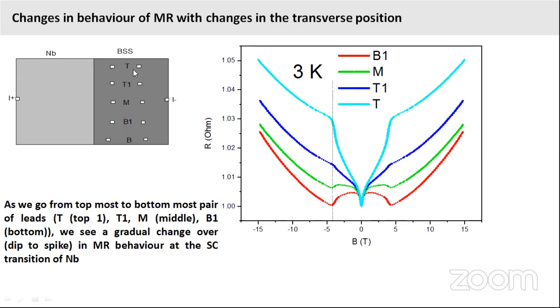As we move from top to bottom, we observe that at the top there is a spiking in the MR, and then as we move down to this T1, there is a decrease in the amplitude of the spiking, and then as we move lower, there is a dip, and the amplitude of the dip increases when we come further to the bottom. This is what we observe.